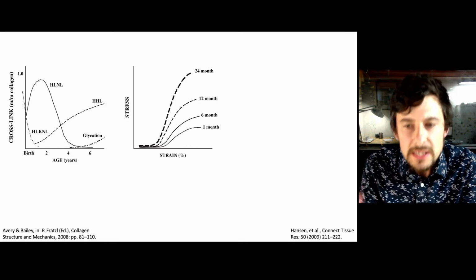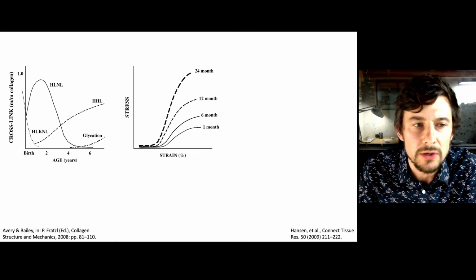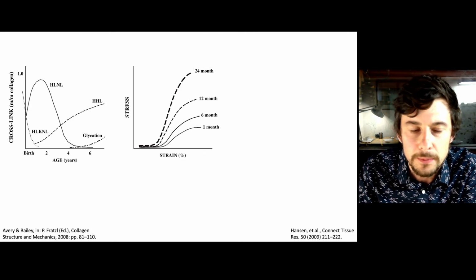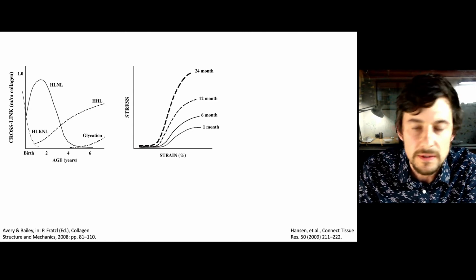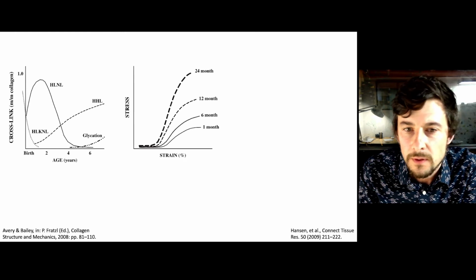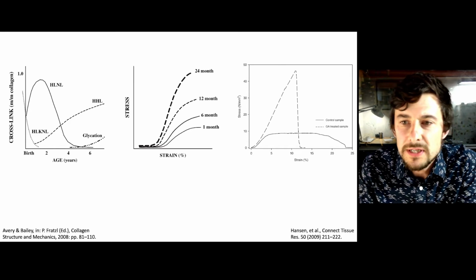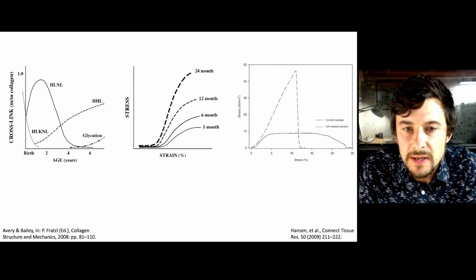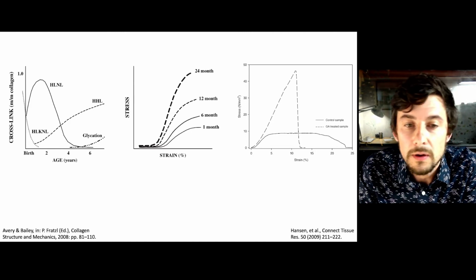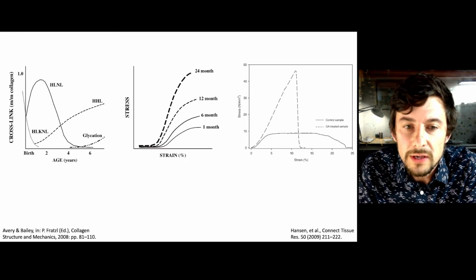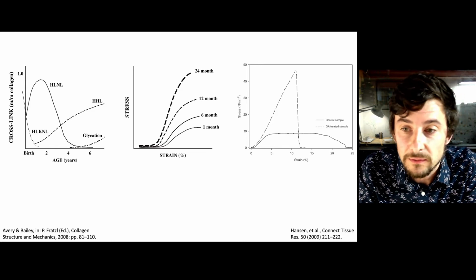And it's really easy to look at this figure and come away with the idea that the relationships between cross-linking and mechanics are very simple. Increased cross-linking gives rise to increased tissue stiffness and increased strength. And that's consistent with the biomaterials literature, which shows that exogenous cross-linking treatments, like glutaraldehyde in this case, give rise to an increase in tissue strength and stiffness, markedly in this case.